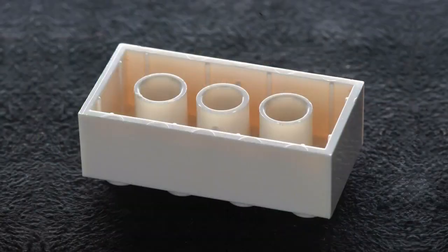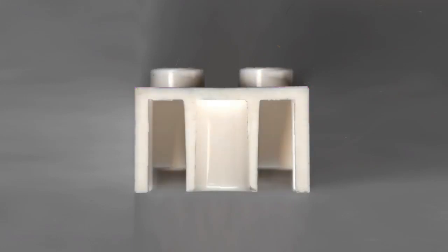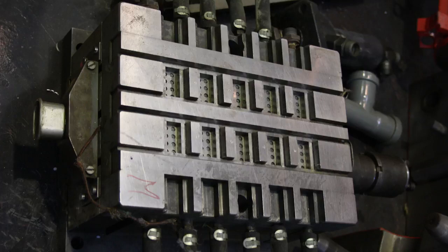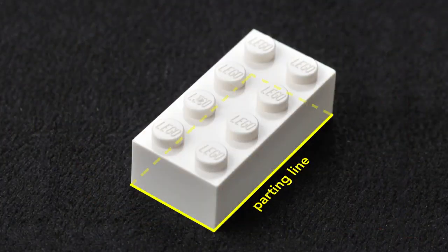The downside is that this setup is more expensive than a traditional cold runner system. On the bottom edge of the brick, you can see ejector pin witness marks. And what's most clever to me is where Lego designs their draft angle. The outside of a Lego brick must be square. So if you cut a Lego brick in half, you can see that these inner supports are thicker at the top than at the bottom. There's a draft angle of about one and a half degrees. This helps the ejector pins push the brick off the mold. The core half and the cavity half of Lego molds are designed so that the parting line is at the bottom edge of the brick. This hides the parting line.